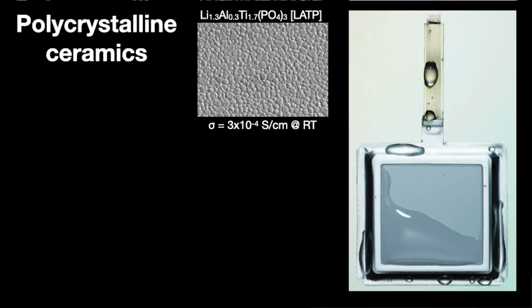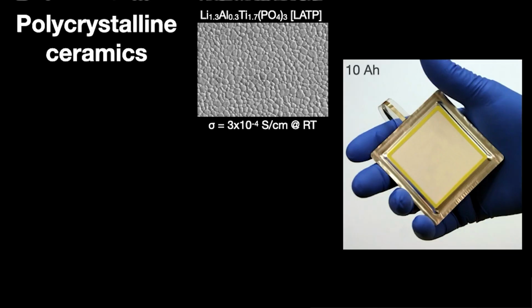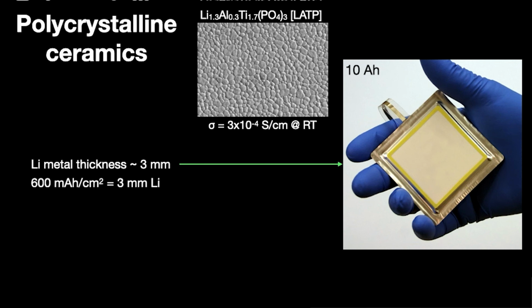So let's first look at polycrystalline ceramics, because Polyplus works extensively in this area. We work with a material known as LATP, which is lithium aluminum titanium phosphate, which is a water-stable solid electrolyte. So we can build lithium metal electrodes, which can be fully immersed in water. And that allows us to build some very unique battery chemistries. So here you see a 10 amp hour negative electrode, which is enabling for a variety of lithium metal aqueous chemistries. But the core of that structure is a lithium metal electrode, which is about 3 millimeters thick. So that's 600 milliamp hours per centimeter squared. That's a lot of capacity per unit area.